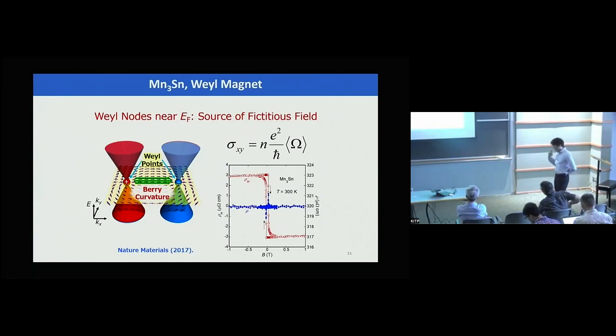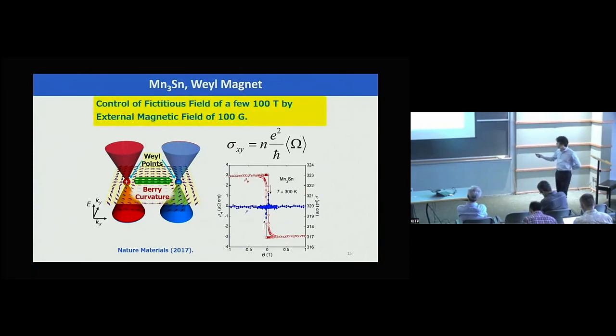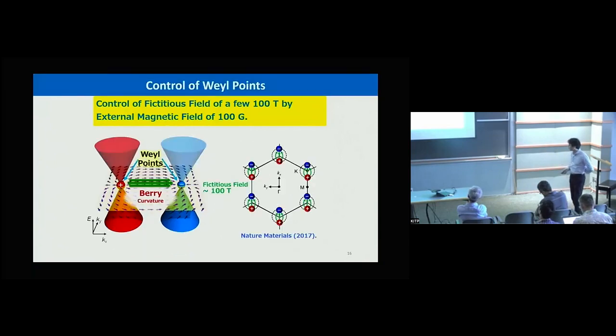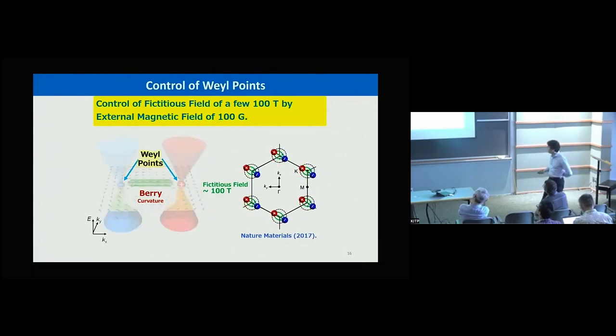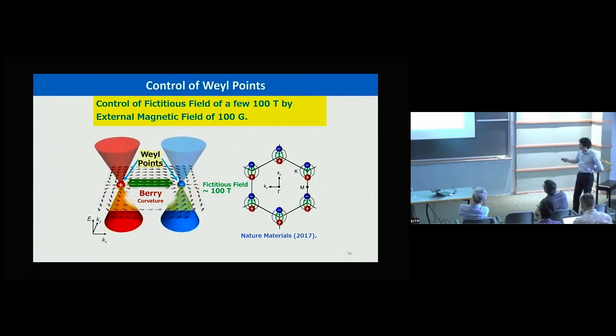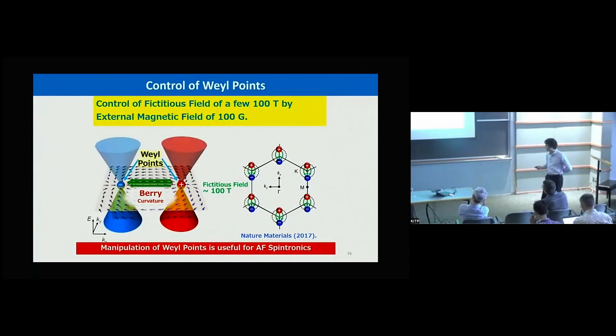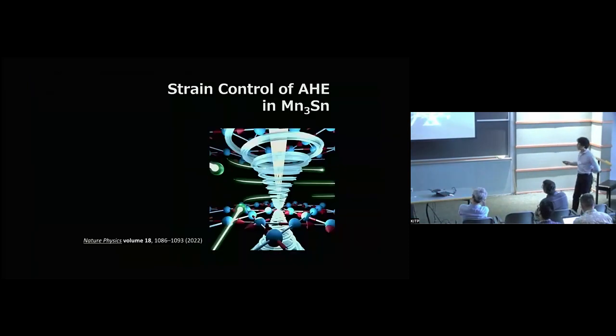This tells us, if we calculate the external field necessary to induce this size of Hall resistivity, say several micro-ohm centimeter, using the orbital, ordinary Hall effect, it requires a few hundred Tesla. So almost like 100 Gauss is enough to control the few hundred Tesla impact on the system. So this is emergent electromagnetism. In order to find further evidence, further phenomena, new functionality, it would be more interesting if we can find other methods than just magnetic field, such as strain or electrical means. So that's what we did, and we're going to go through some recent work on the strain.